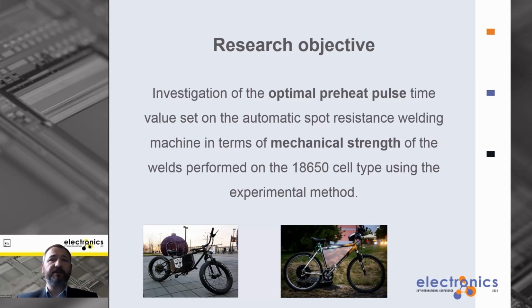So the research objective is formulated as investigation of the optimal preheat pulse time value set on the automatic spot resistance welding machine in terms of mechanical strength of the welds performed on the 18650 cell type using the experimental method. Here we have two constructions made in our laboratory for different tests.